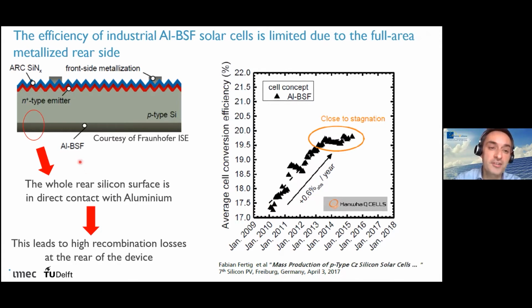And the limitation is actually at the back, at this aluminium BSF that gives its name to the device. Because if you look at the rear, the whole rear of the silicon is in direct contact with the aluminium metal. And this leads to a lot of recombination losses at the rear of the device. This does not really allow you to make devices with efficiency higher than 20%.